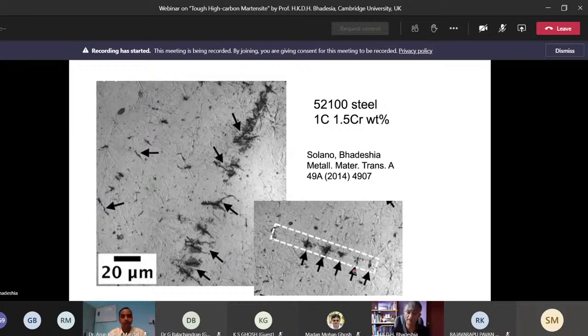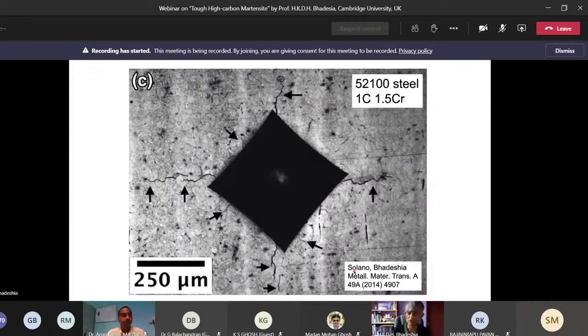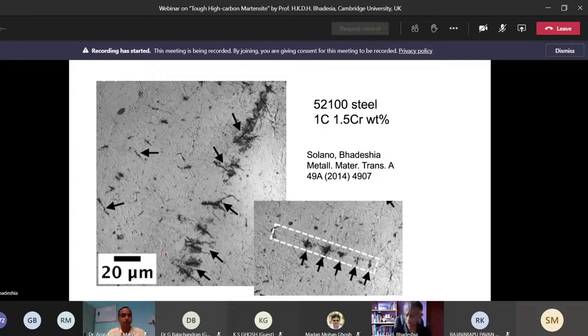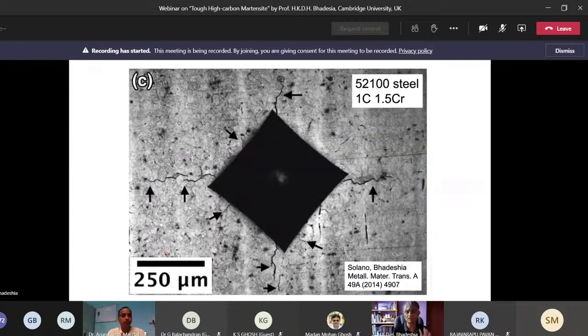So that is not going to give you a good performance in terms of toughness. And even if you take this steel and you just put a hardness indent on it, that will cause the surrounding material to crack. So it is absolutely true that in the structure illustrated here, where I have martensite plates which are many hundred micrometers long, the plates will crack spontaneously on quenching. And therefore, your material will tend to be brittle.